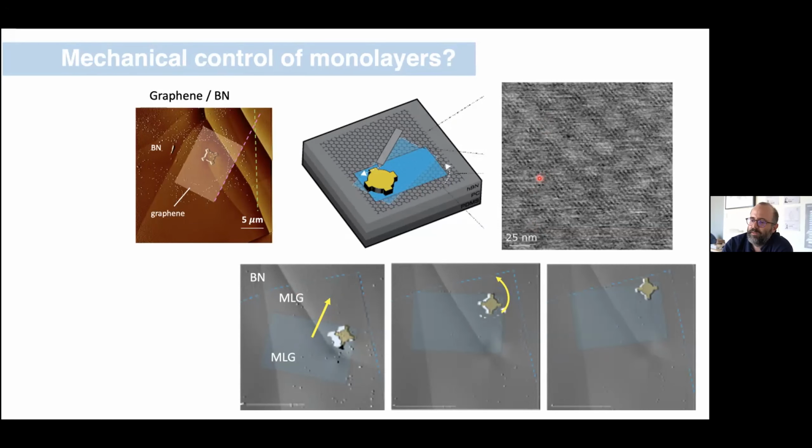And now what we see is that there's a beautiful moire pattern. It looks quite uniform. And if you look carefully, you'll see that there are 2 length scales in this moire pattern. One length scale is coming from the graphene, 1 degree misalignment. And the other length scale is coming from the fact that in this particular case, the bottom graphene layer ended up being aligned to the bottom BN layer. So we actually see this interesting interference of 2 moires, in this case, graphene-graphene and graphene-BN.